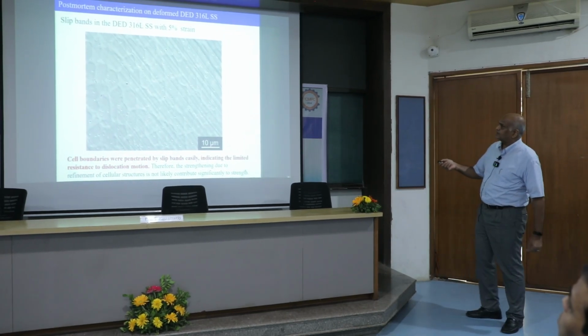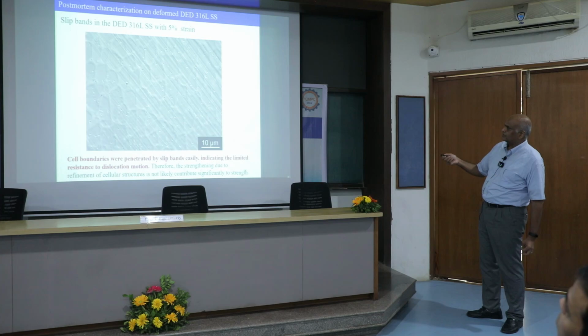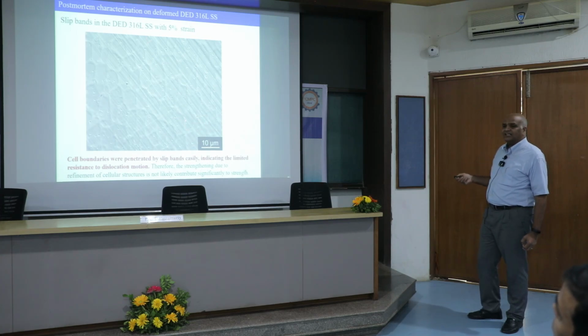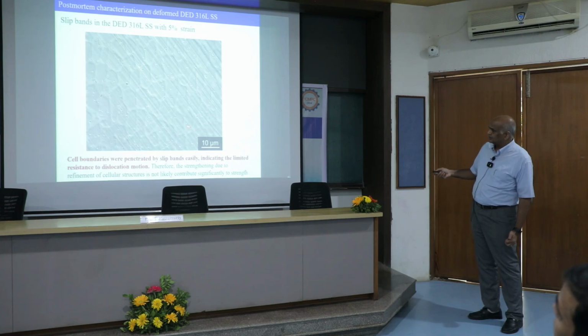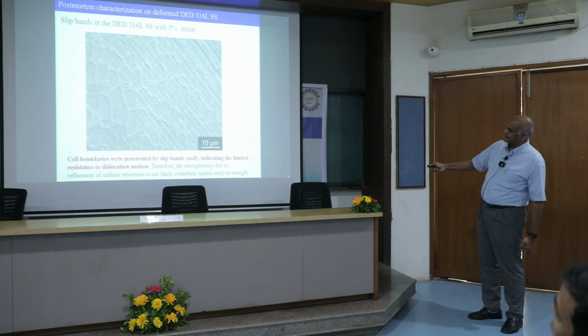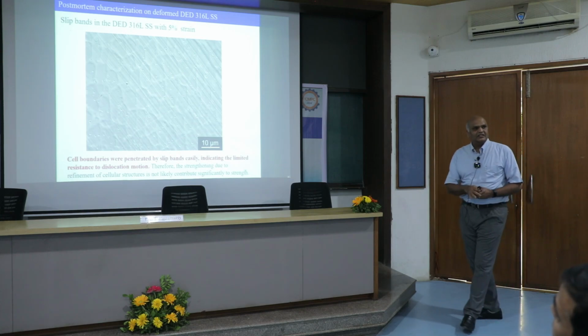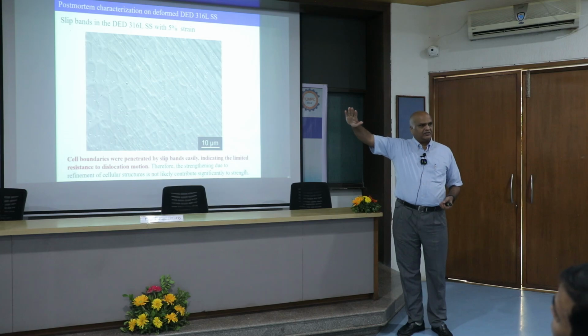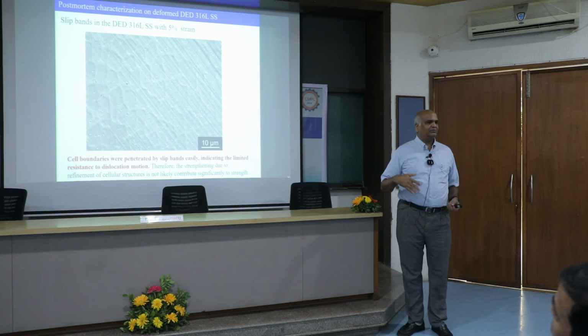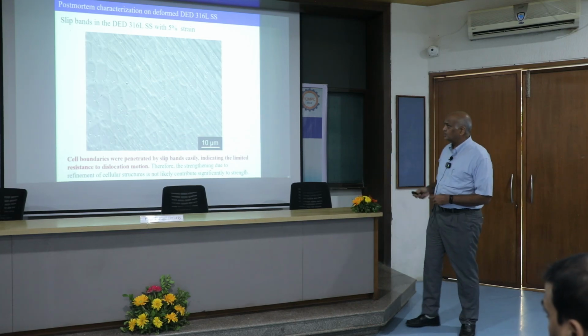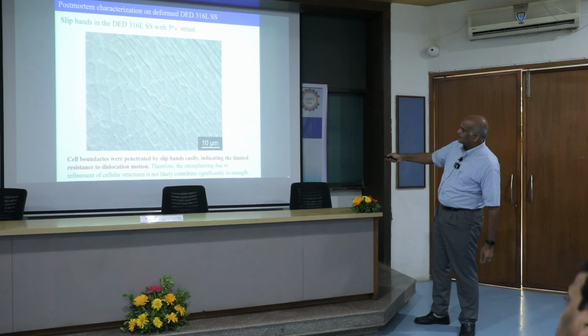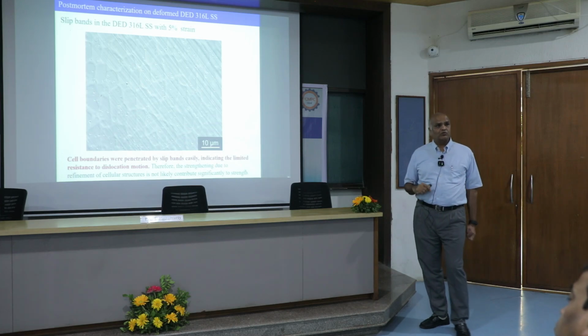Here is DED, directed energy deposited 316L. There is some silicon in this material and it oxidizes, so you see silica particles, those are the particles. But what you need to focus on are these traces. These are what we call slip traces. When dislocations come out of the free surface, you can see them. This is planar slip that is active. I hope you can see the cell walls in the background, right? All these cells, and these dislocations are cutting through. So what we showed is that.